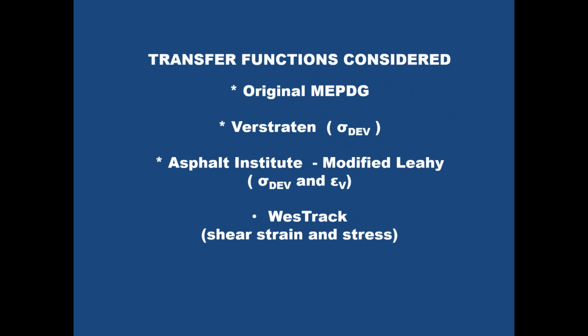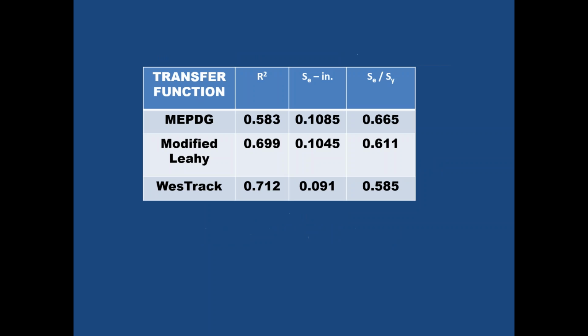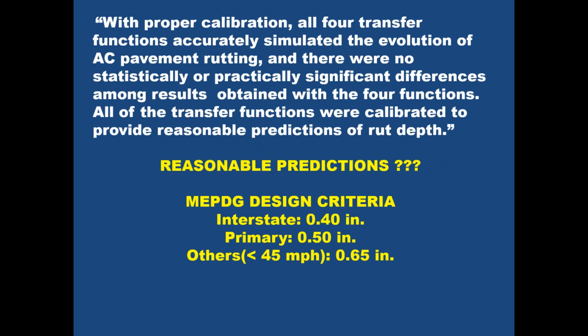...was carried out in Reno, Nevada many years ago. They did a lot of sophisticated work with repeated shear strain testing, and that model takes into account stress. Okay, these are the R squared they found for the databases. The standard errors, as you can see, they're all about 1/10 of an inch, the S sub E over S sub Y term, but they all turned out to be about the same. And basically they say, look, if you reasonably calibrate these models, they'll work. Okay, calibration is not an easy thing or a cheap thing to do.